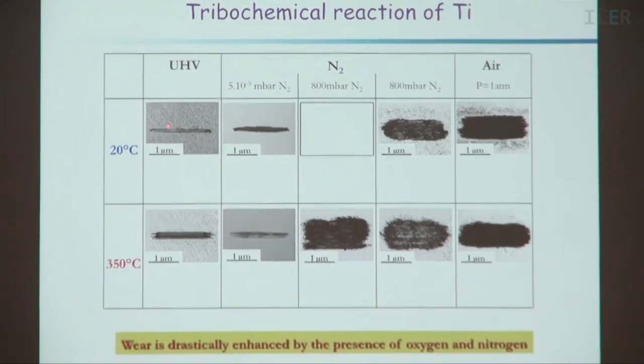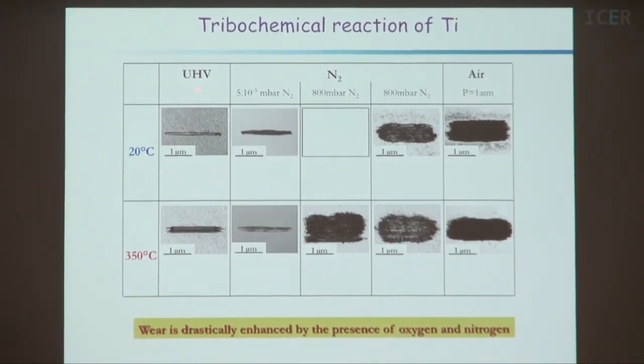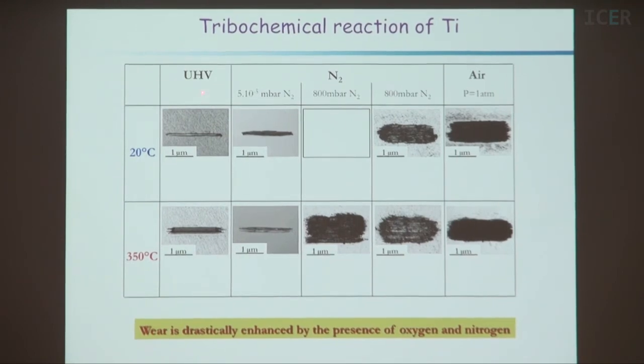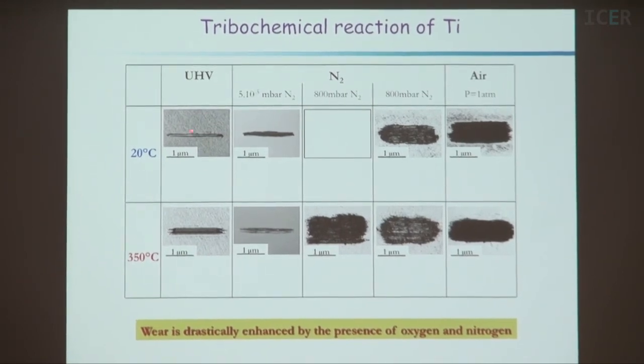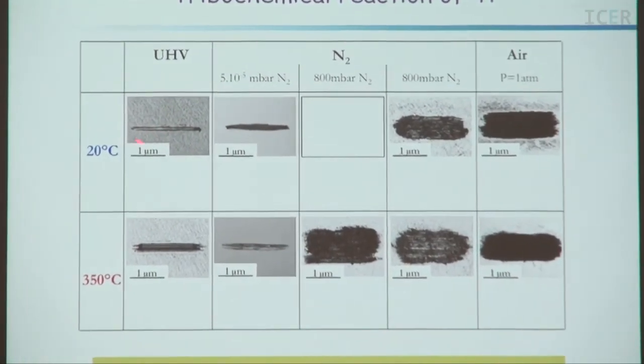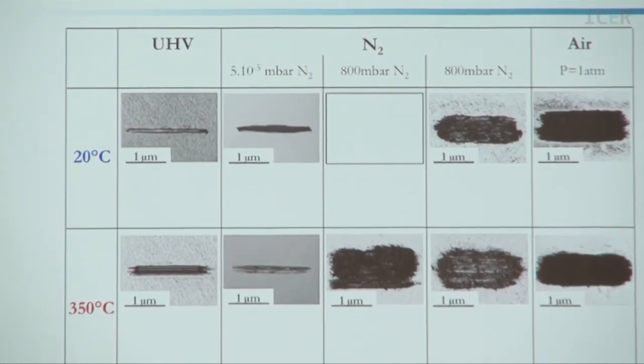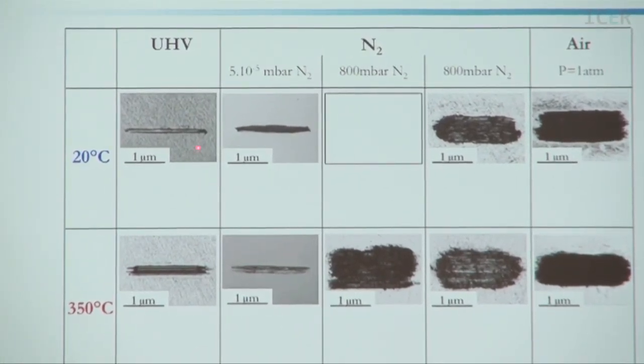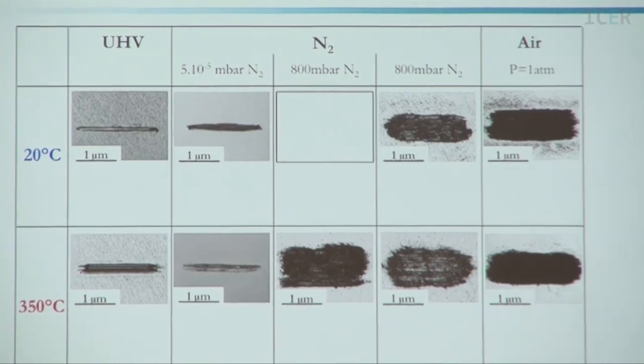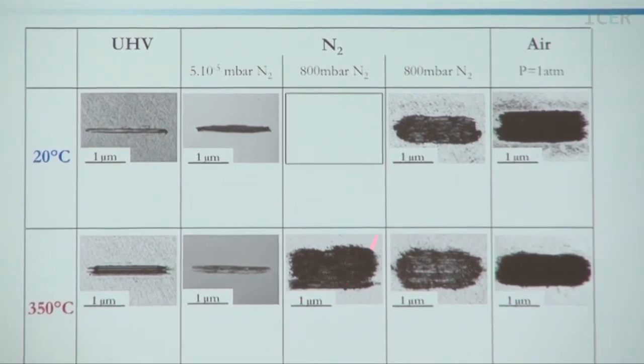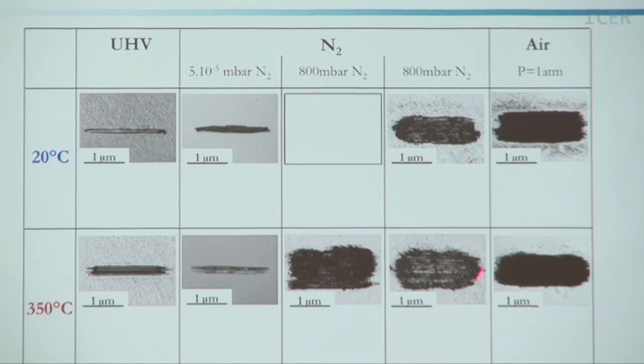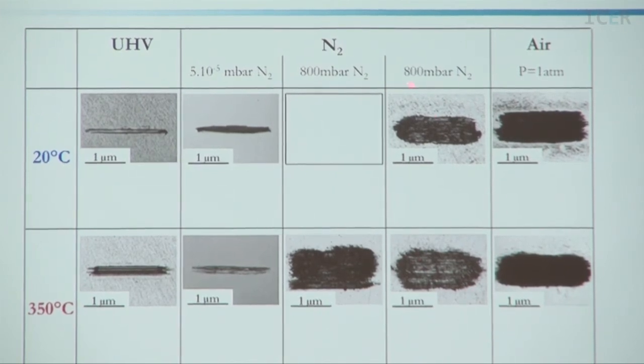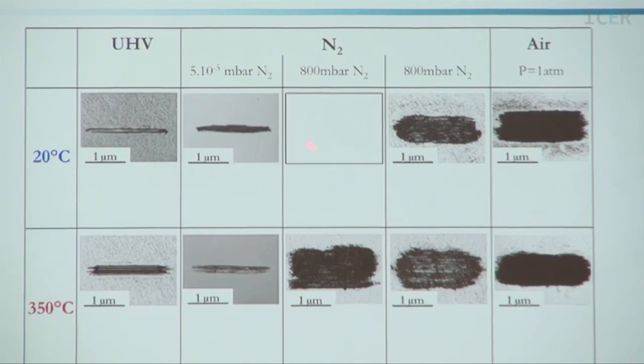This is very interesting. This is friction of a titanium alloy in high vacuum. You can see that there is a very small wear scar. This is the image of the surface after the friction test. Wear is very small. But if we work in high pressure of nitrogen, here you can see 800 millibar, a lot of wear appears. And in air the same. Sorry, we have no image here.